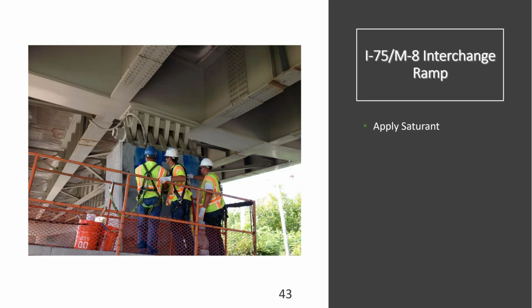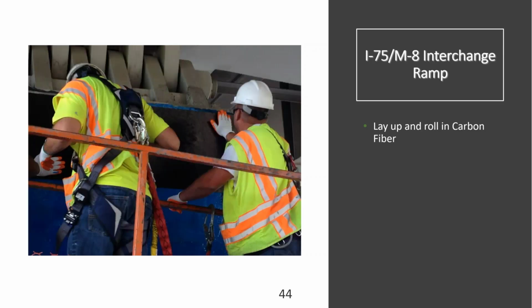The saturant gets applied just basically using standard paint rollers that you would use. And then every manufacturer, based on the thickness of the fabric you're using, will give a recommended coverage rate. For the fabric we were using, we estimated a rate of 45 square feet of coverage per gallon of epoxy. So once the first coat of saturant is applied, we applied the fabric to the saturated surface.